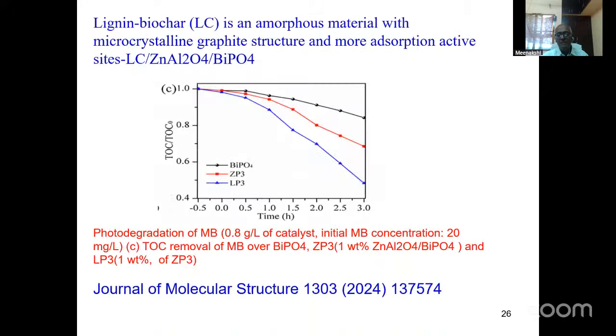So now let us see some examples of applications. Photocatalytic applications: you can see that lignin biochar, that is from wood, is actually an amorphous material. Using the lignin biochar, photodegradation of methylene blue is done. Zinc aluminate and lignin biochar alone show lower efficiency, whereas this composite, lignin biochar zinc aluminate bismuth phosphate, has the maximum efficiency in the degradation of methylene blue.